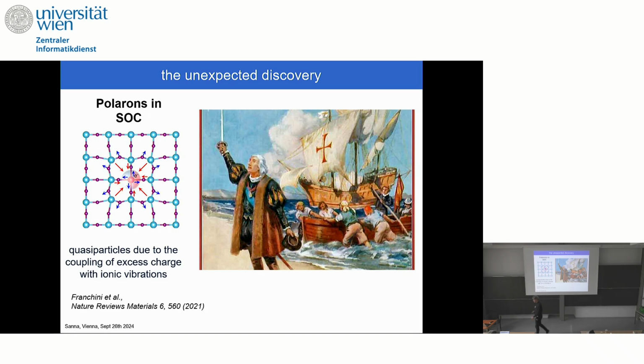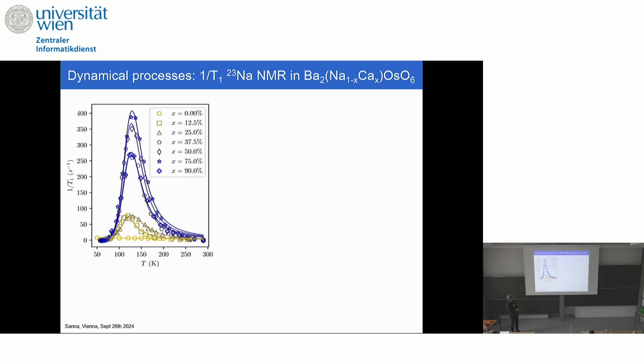I must say that we didn't expect that from the experimental point of view. When we discovered the peak, by analogy with manganites, where the polaron exists and there is a similar behavior, similar activation energies, etc., we suspected that there was a polaron. And when I talked to Cesare, he told me that also from our calculation we can see that there is the possibility to have polarons in this system, and we could measure everything as a function of the doping. You can see that the undoped material doesn't display these peaks, so probably the sodium counterpart doesn't have the polaron.